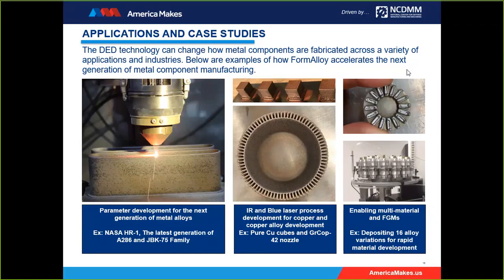Something unique that we've done is significant work when it comes to pure copper and copper alloy deposition. The top middle image contains pure copper cubes produced by our IR laser deposition process. This may not sound significant as copper is a common material used in a variety of parts, but due to the reflectivity of the material, it typically absorbs less than 10% of the IR laser's energy. However, the cubes that we produced here at FormAlloy had 99% density and had electrical conductivity and tensile properties within 3% of the typical oxygen-free property.